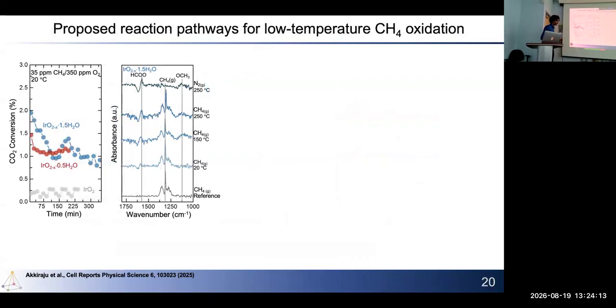And here are the results for methane activation at room temperature. So the iridium oxides, earlier, we could run them at 120, 125 degrees and see that methane was getting activated. But this room temperature result here shows that you already have conversion to CO2, even at room temperature with these two new oxides here.